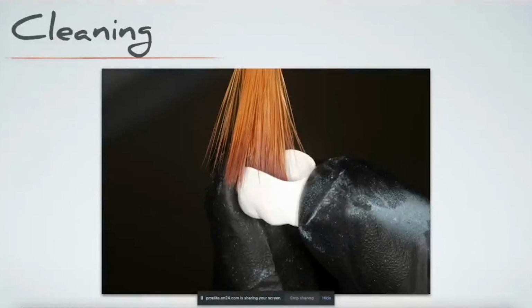The other thing I would warn you about using air on this instead of something like a horsehair brush is that when you use air, it's very easy to have this thing blow across the room, and it's very fragile at this point. So if it were to hit the floor, hit a countertop, fly across and hit a wall, something like that, it would be very easy to break or chip or even take off a large chunk of the restoration. So we simply just dust it off with a large brush and get it ready for sintering.